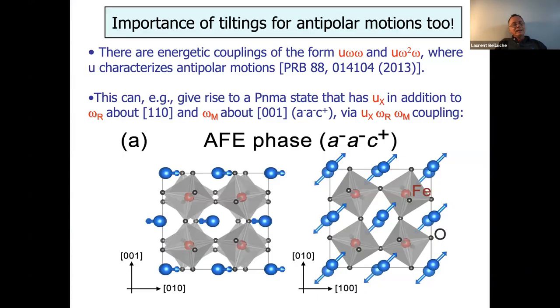Now, why is tilting important? It's also important for antiferroelectric systems because there are couplings of a form, let's say U omega omega or U omega square omega. Omega is about tilting, as I told you before, but U now is about antipolar motions. For instance, if you look at PNMA states, which in Glazer notation is A minus A minus C plus, it means it has an antiphase tilting about 110, that's why you have A minus, and in-phase tilting about the C axis, that's why you have C plus. But there is a special coupling. It's called U_X omega_R omega_M, and this brings U_X into play, and U_X is antipolar.